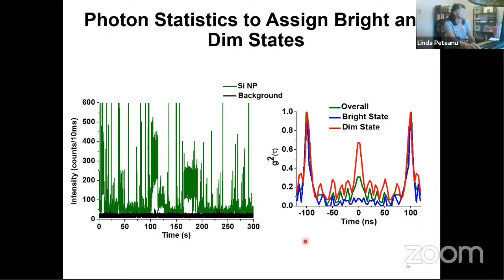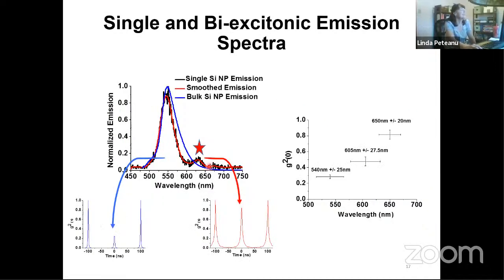has developed. We can also show that by looking more conventionally at what these emissions look like. We took the emission from a single particle and dispersed it, so we have the emission of a single silicon nanoparticle superimposed on the bulk emission spectrum. Once you look at a single molecule, you can see some of the finer details, and one of those is an emission bump at about 625, which is rather small compared to the main feature. The main feature, again, is a really high quantum yield. This is the ligand-derived emission, and its quantum yield is about 90%. But this is a reproducible small feature in the region that others have assigned to a biexcitonic band within a silicon nanoparticle that does not have emissive ligand states.